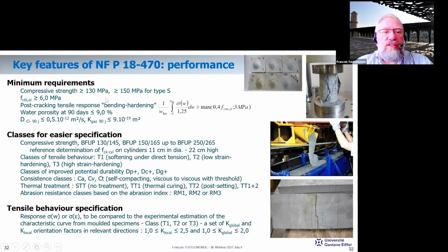Let's go to the material standard. It gives the minimum requirements to call a material UHPFRC. As I've said before, there's a criterion in terms of compressive strength higher than 130 megapascal, and 150 for structural applications. A minimum elastic tensile strength of 6 megapascal. A minimum non-brittleness rule, expressed as a post-cracking tensile equivalent stress between 0 and 0.3 millimeter crack opening, higher than 40% of the elastic limit and higher than 3 megapascal.